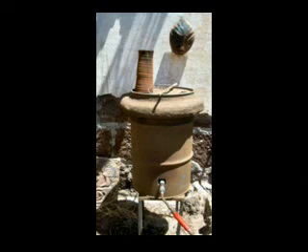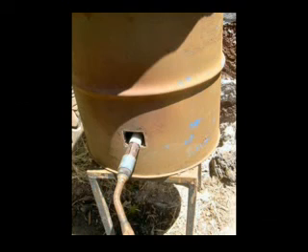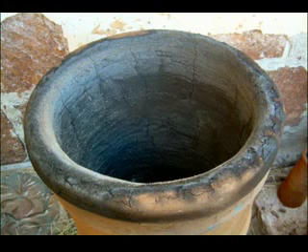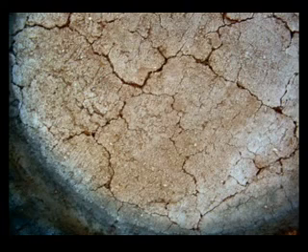There you see the whole assembly provided with a propane gas weed burner. You can also use a petroleum nozzle burner which is easy to make and even cheaper. This kiln was made from recycled materials, costs practically nothing, is very cheap, very easy, and works very well. I'm very content with the result. When I fired it, the temperature inside was much above 1000 degrees and I could easily touch the outside wall without burning my hand. Look inside — it's totally reduced clay, and there are some little openings from broken clay but it doesn't matter.